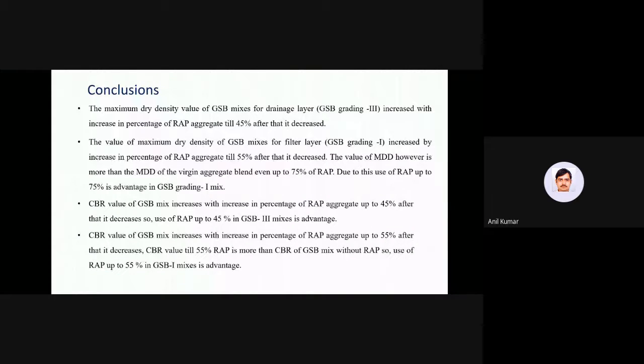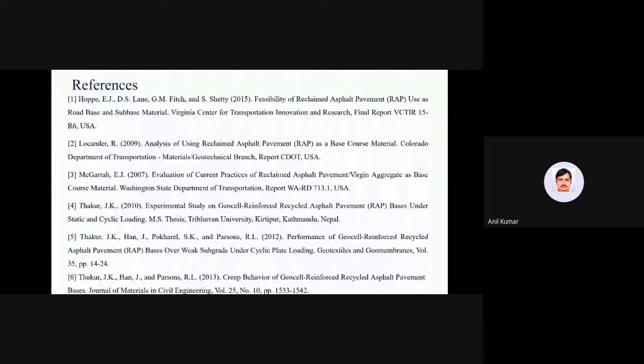Then the conclusions. The dry density value of GSB mixes for grading 3 shows the best result at 45% RAP, and for grading 1 it is at 55% RAP. Also for grading 1 we can use up to 75% RAP, as the MDD value is higher than the natural aggregate value, even up to 75% RAP. Then the CBR values for grading 3 and grading 1 are best at 45% and 55% respectively. These are some of my references.